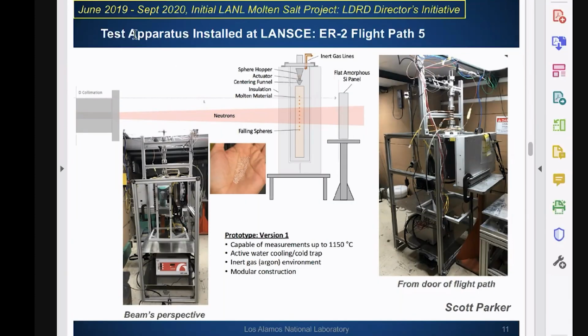I showed you that the time frame of this project was rather short. And so this is the idea. You're dropping spheres. This is my hand holding these spheres, 2 millimeters in diameter, through an actuator with a centering funnel. This is controlled remotely from outside the flight path, and then it's dropped through the molten material and detected by the neutron beam.